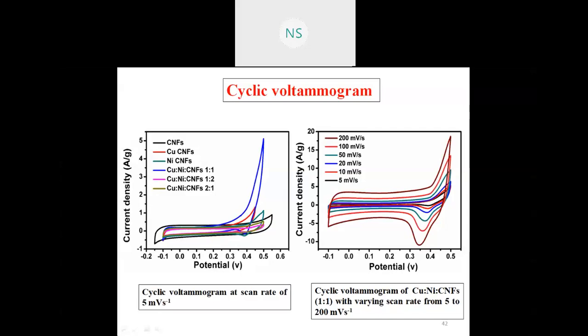If you look into this blue line, that is the copper nickel carbon nanofiber 1:1 ratio, it is the best option, with scanning done at 5 millivolt per second. So the current density is maximum in the case of the 1:1 ratio. And when we talk about this one, the scan rate varies from 5 to 200 millivolt per second. That blue line, from 5 to 200 millivolt per second, shows a complete reverse way. That is done for the 1:1 copper nickel carbon nanofiber. Next.